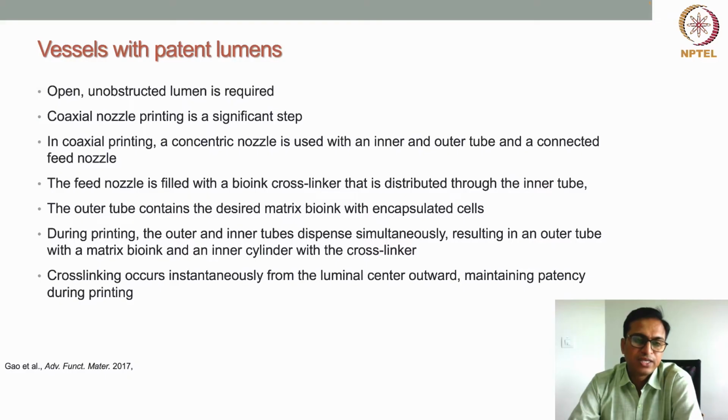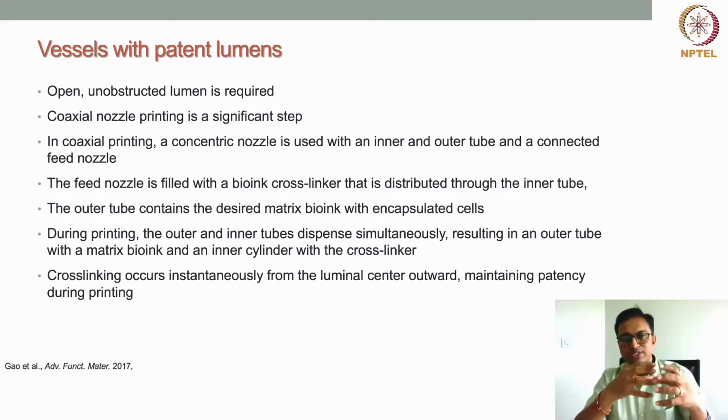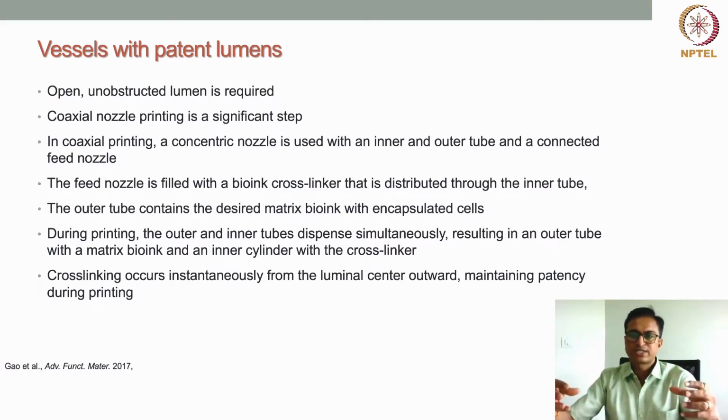But suppose I extrude the bioink through the outer channel, and through the inner core I feed the cross-linking solution. Then the crosslinker will cross-link the bioink that is coming out as a tube-like structure, and the inside will be filled with the crosslinker. So we get a tube-like structure filled with crosslinker inside, and the structural patency can stay intact because of the crosslinker present.